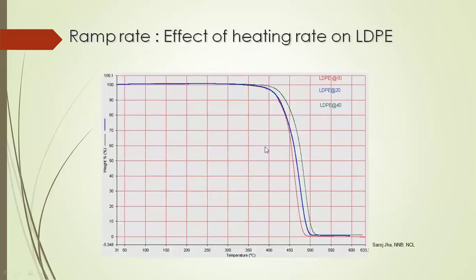Ramp rate, heating rate. These are the samples. Red is heated at 10 degrees centigrade, blue is 20, and green is 40 degrees centigrade per minute. So if you see here, the onset of degradation shifts to higher temperature if you heat at a higher rate. Actually, the degradation onset of the sample is around 355, but if you degrade the same sample with a higher heating rate, you will get 400 degrees centigrade as a degradation onset. So always, if you want to find out the degradation onset, run the sample at a lower rate.